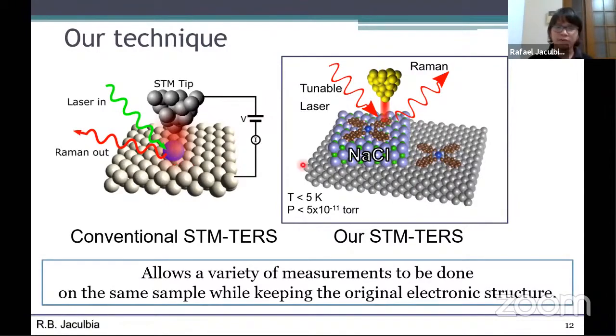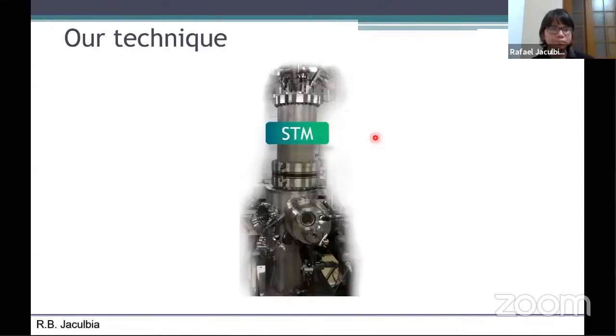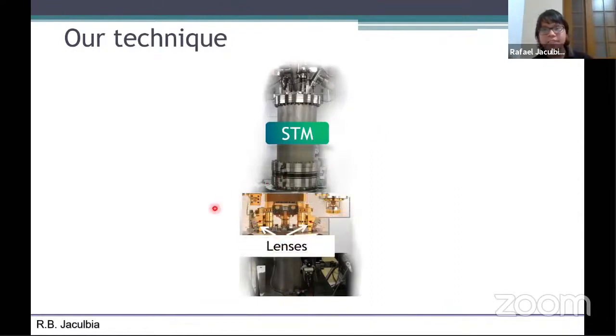Moreover, our technique could allow a variety of measurements to be done on the same sample while also keeping the original electronic structure. So when you put the molecule near the metal, the molecule's electronic states hybridize with the metal, and therefore you cannot get the original electronic structure. But as I will show later, with this technique, the original electronic structure is preserved, so we can study the original properties of the molecule. As I said, our technique is based on the STM. So we use the low temperature ultra high vacuum STM, and this STM is a little special. We have lenses inside the ultra high vacuum chamber, and this is for detecting light and introducing light into the STM tip junction.